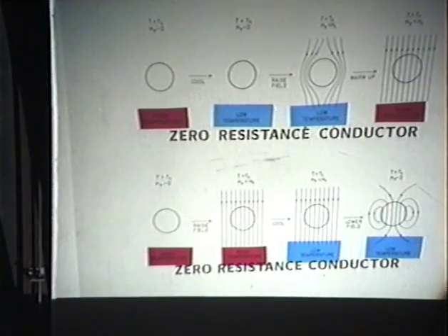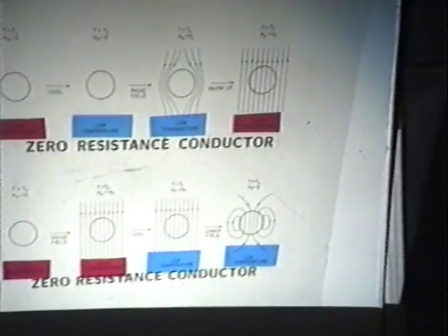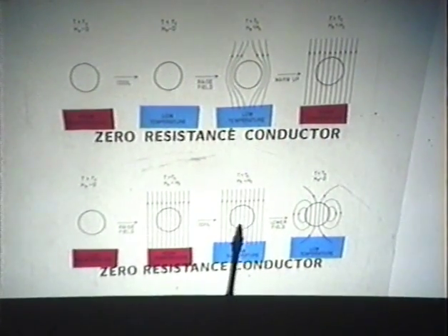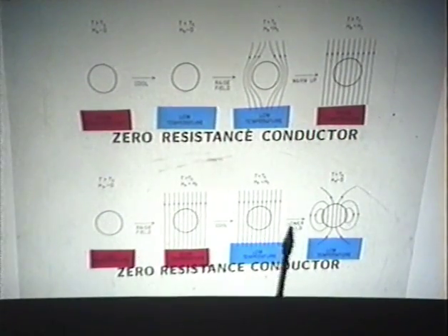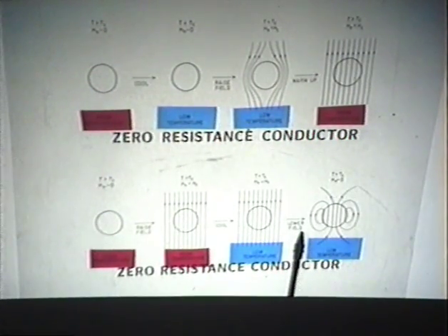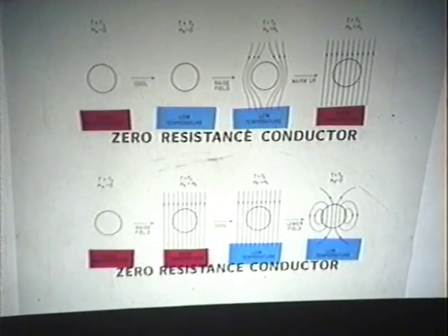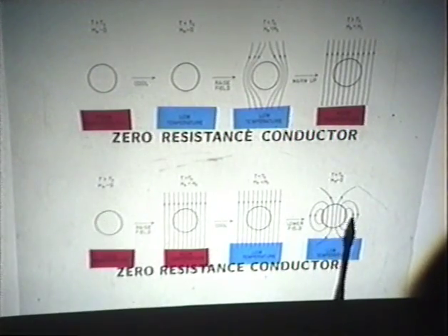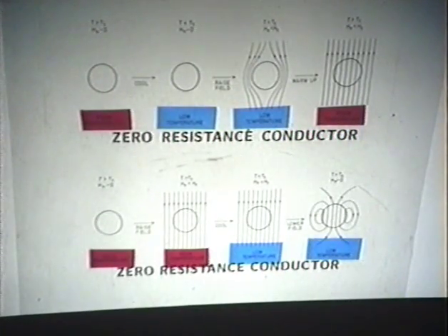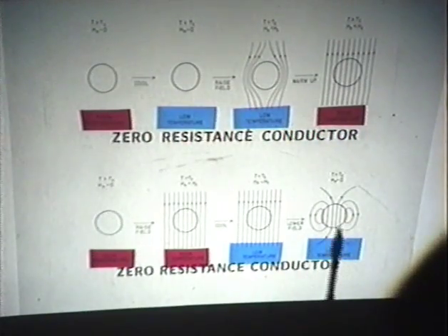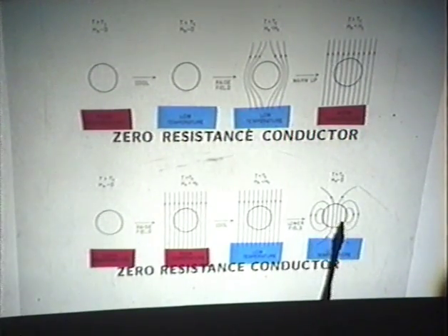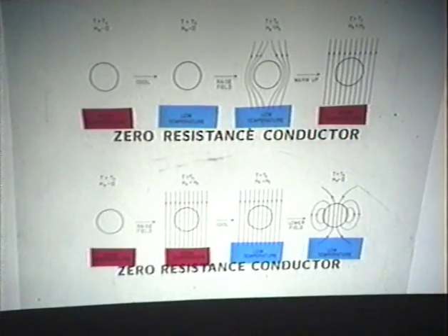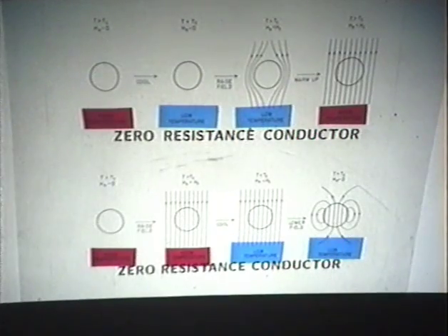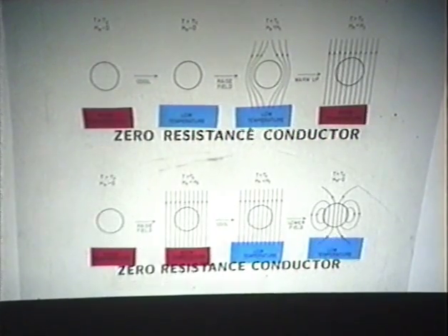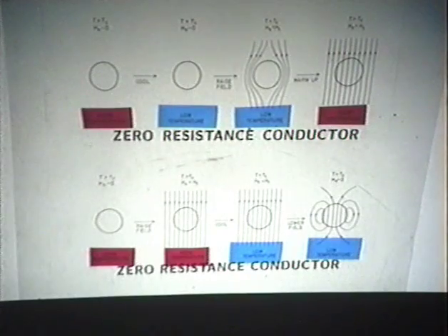And so you don't expect anything to take any notice, because things only take notice of changing magnetic fields, not static ones. So then you'd expect that when you lowered the magnetic field, now you're talking about a change in magnetic flux, and so you would induce eddy currents again, which would try and hold up, and would in fact hold up the field that you're trying to take away, to preserve it inside the superconductor, and the eddy currents would persist forever. I guess you shouldn't call them eddy currents anymore because they're not eddying, they're staying there. And there you've magnetized it effectively.